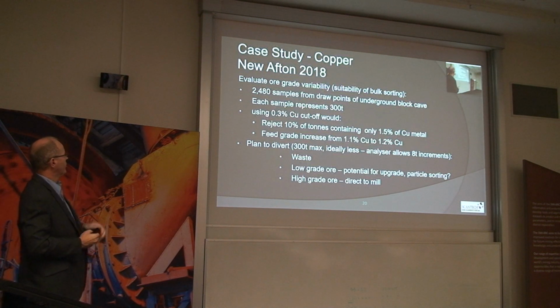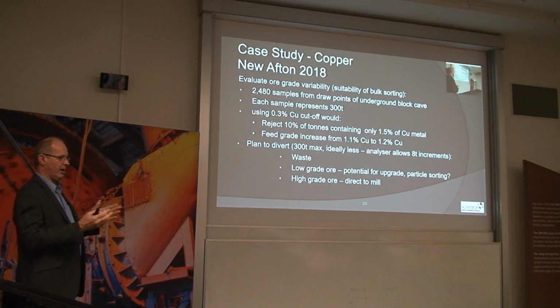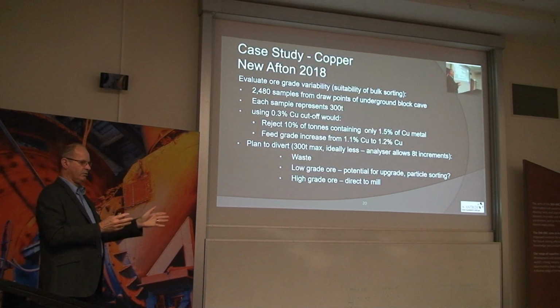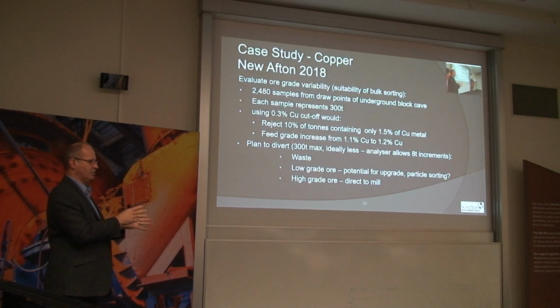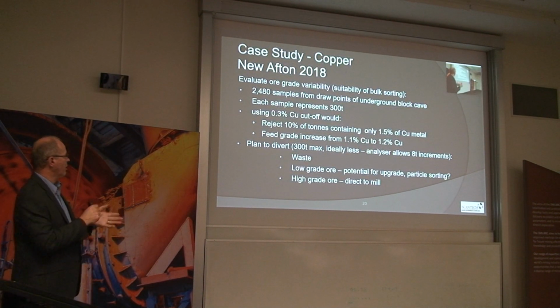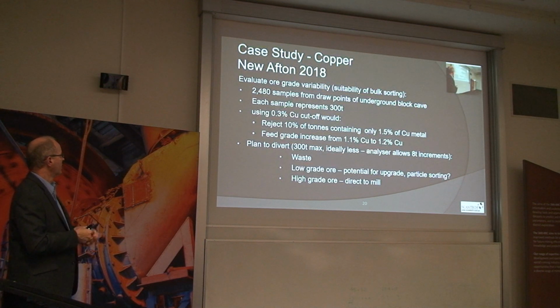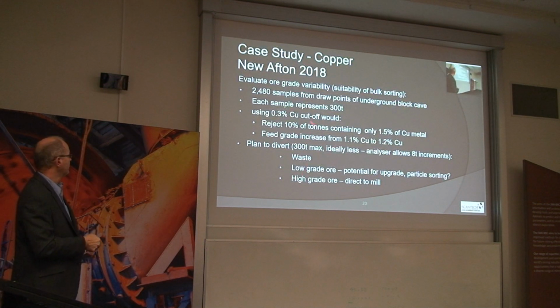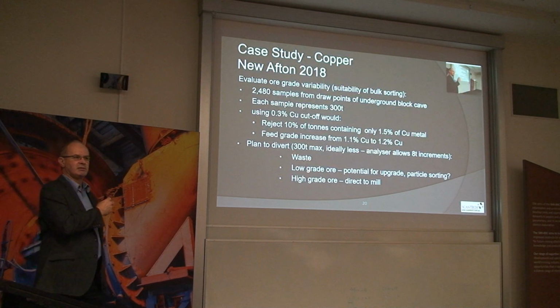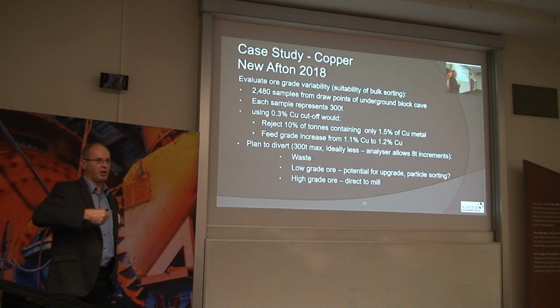So they said, okay, if we use the 0.3% cutoff, how much would we have diverted or selected as being unsuitable to process, and how much copper metal would have been in that material? So you can see that they would have diverted 10% of the tonnes, but only lost 1.5% of the copper metal, and the feed grade would have increased in the 90% of the material from 1.1 to 1.2% copper. So they said, great, that's all the justification we need to go ahead with the project.